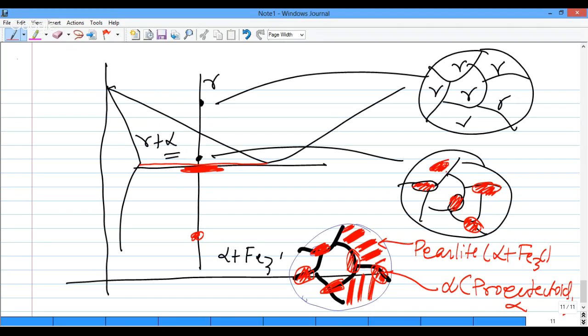If you want to find its fraction, you should draw the tie line there and find the fraction of alpha, which will be this arm divided by the total arm. The fraction of alpha which you get just above the eutectoid temperature will be the fraction of proeutectoid alpha just below the eutectoid temperature. Since this curve is almost vertical, that fraction will not change much as you cool. So that is the fraction of proeutectoid alpha which you will have at room temperature.